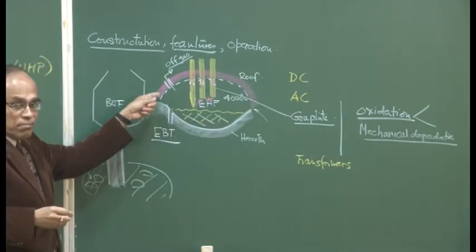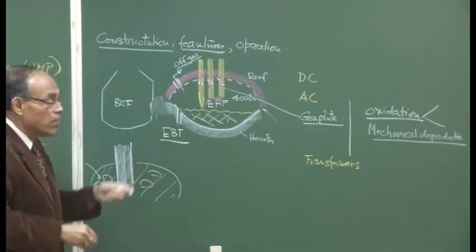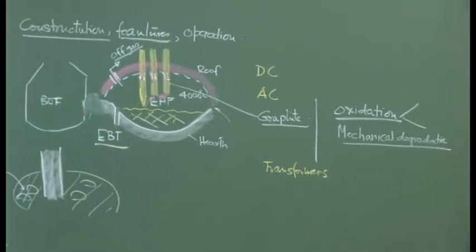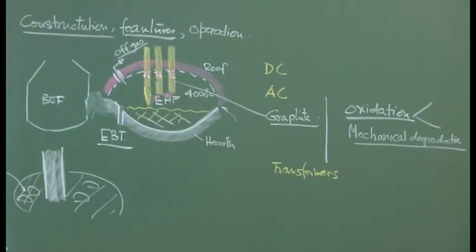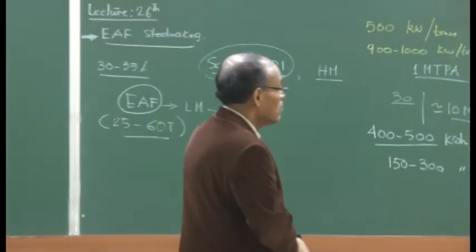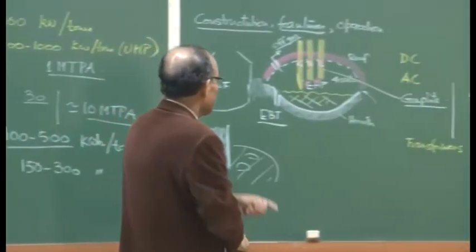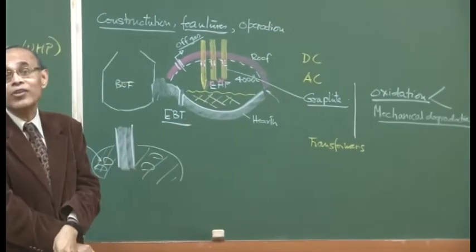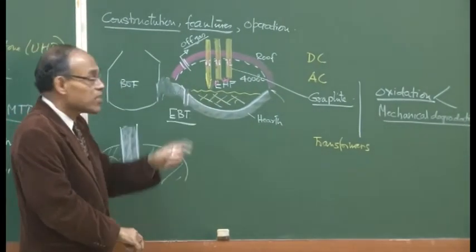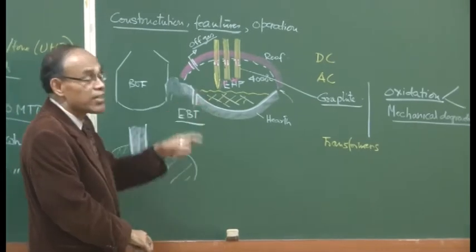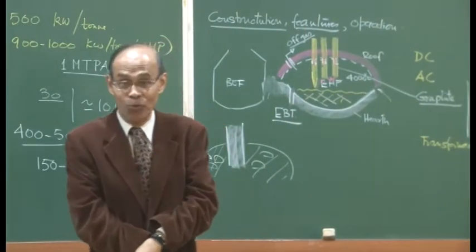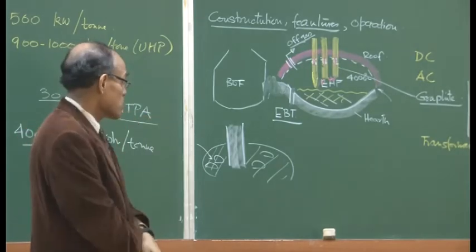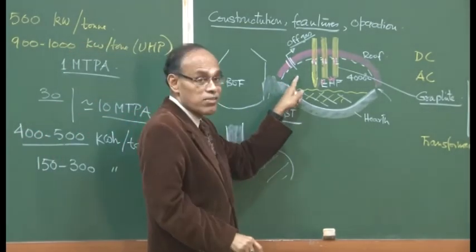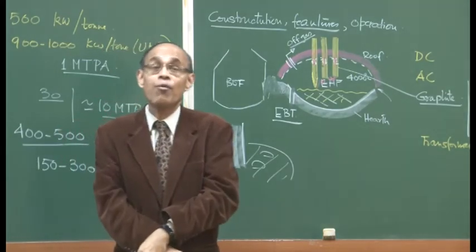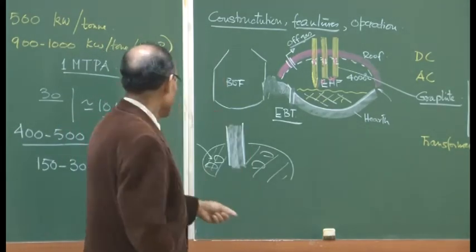the off gas as usual contains dust etc., and most importantly the off gas in this case, because we are using scrap, can contain dangerous elements. Okay? So, I know of a case where the scrap contained chromium, and then because of the oxidation environment, the exhaust gas was found to contain hexavalent chromium, which is a very dangerous species to work with. So, the off gas treatment is very important in an electric arc furnace, because your basic raw material